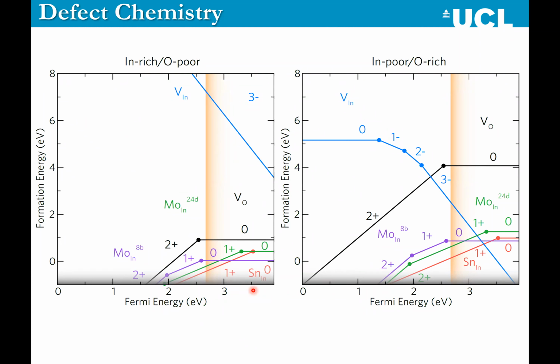So when we calculate the formation energy of defects, we normally plot them in these types of diagrams. On the y-axis, you have the formation energy of the defect, and on the x-axis, you have the Fermi energy, which ranges from 0, which is the valence band maximum or the HOMO, to this orange line, which is the position of the conduction band minimum. And then this goes up just slightly above the conduction band minimum because we wanted to see where these types of dots appeared. So this is the formation energy of a defect versus where the defect states will be positioned in the bandgap.